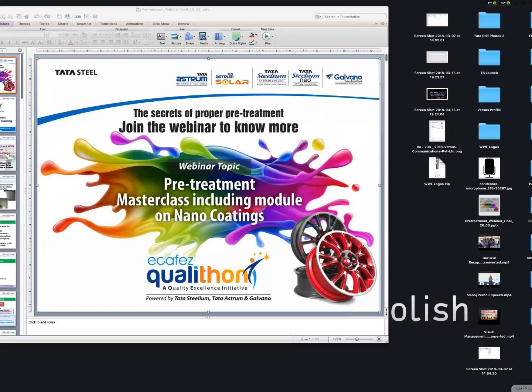Next question is Mr. Sridhara came again. Why are black spots observed after plating in HRPO material? Basically, these black spots may be because pitting is there on the original HR material, or in your HRPO material, 100% of your mill scale is not removed. That is the reason sometimes you see those black spots.